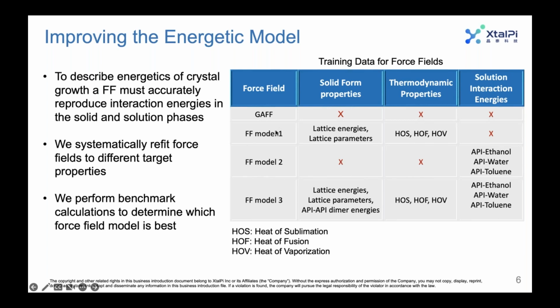In this table here, I've got 4 examples. One is the GAFF force field, which is an out-of-the-box force field. It's not specifically parameterized for any of these properties. The next 3 force fields start from the proprietary XtalPi force field, and then we do some tailored fitting specific for the problem. For example, force field model 1 was refit to lattice energies and lattice parameters, and also some thermodynamic properties. Force field model 2 was fit to API solvent interactions, and force field model 3 was fit to the solid form properties, the thermodynamic properties, and also the solution interaction energies. I'll come back to this in a moment with one of the examples.